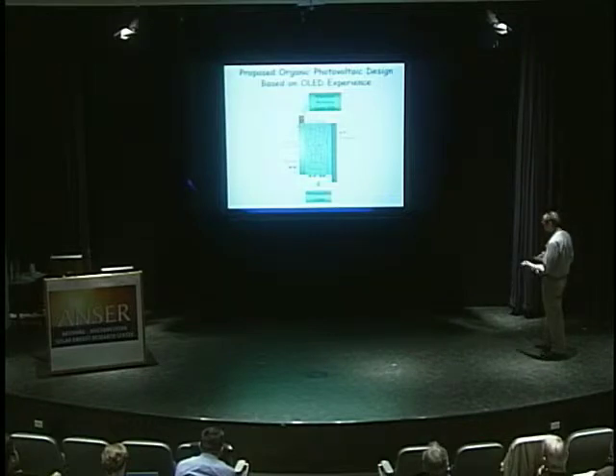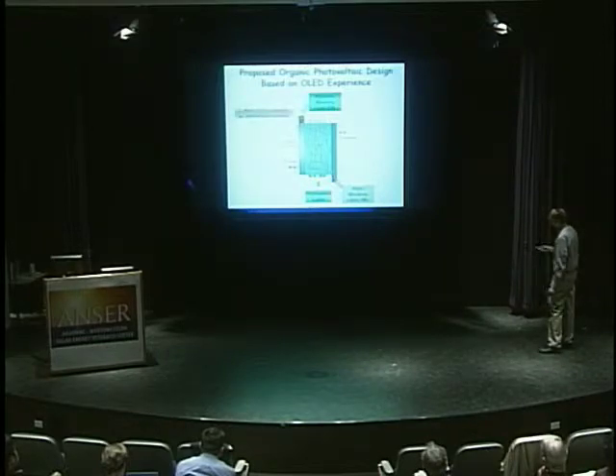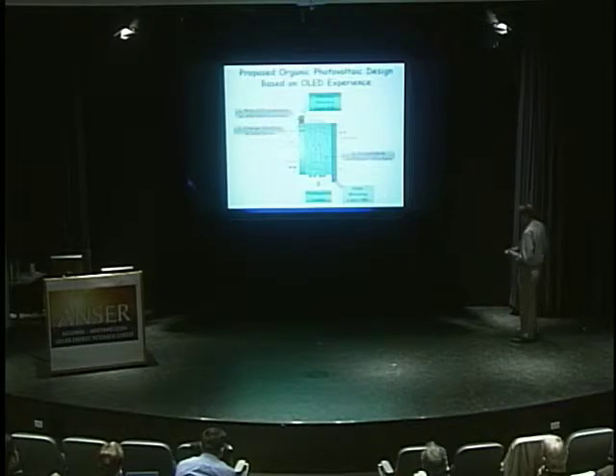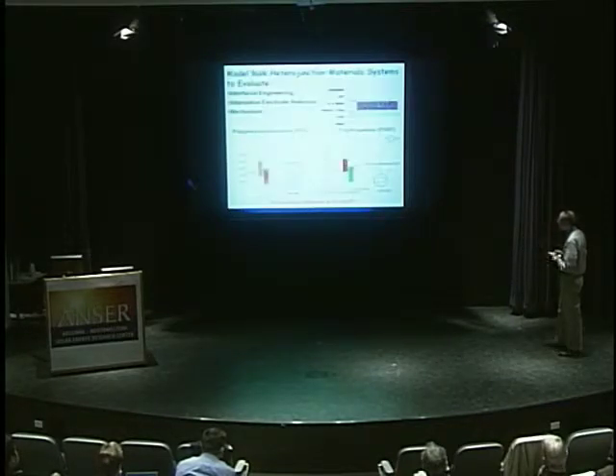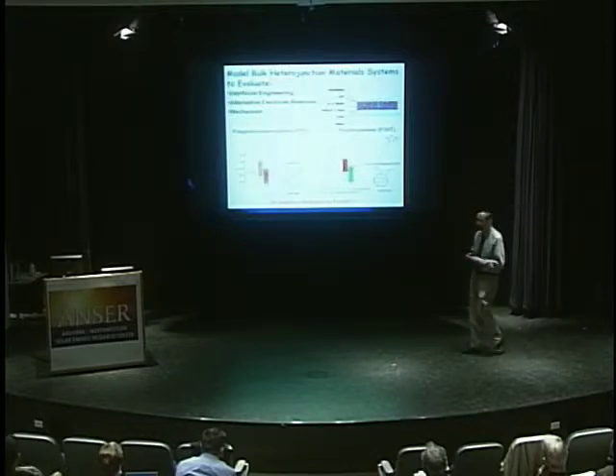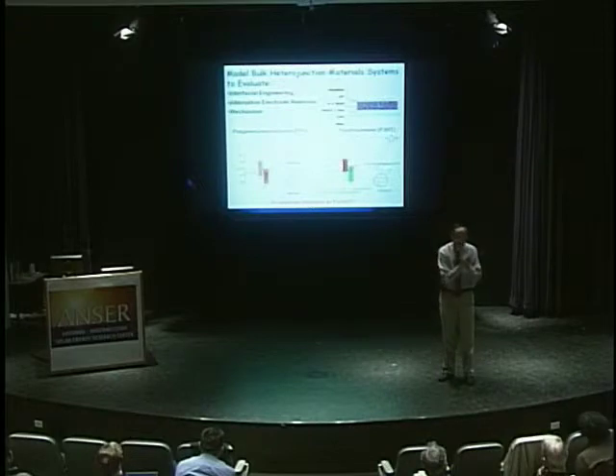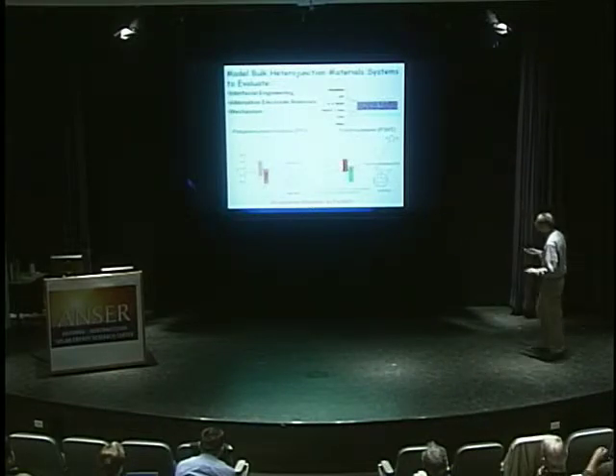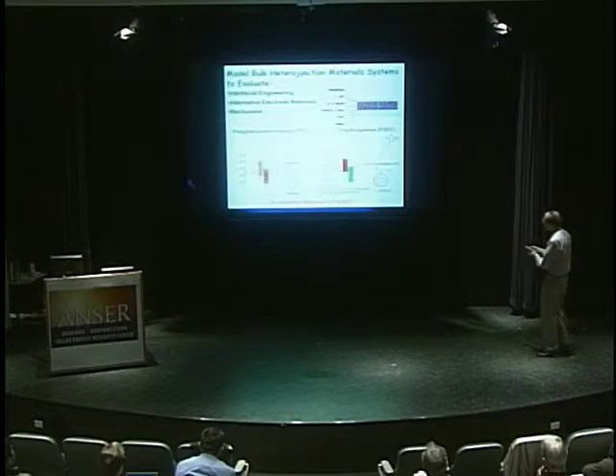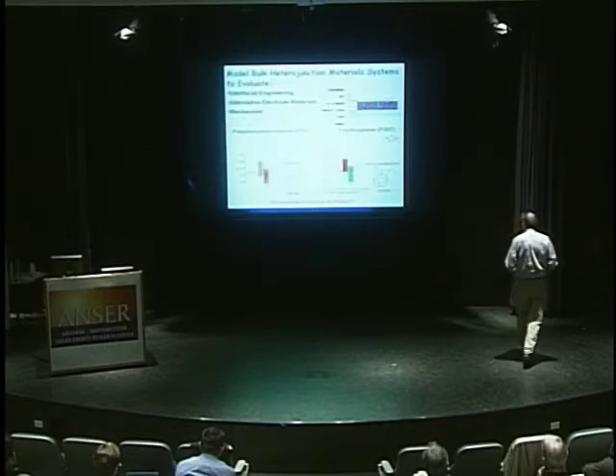Likewise, the photoactive layer, obviously we're going to need that. You can imagine by the same kinds of approaches putting in a hole blocking layer. New TCO materials as alternative anodes. I'll get into that. As I said, indium's in short supply. Charge blocking at the interfaces. And ultimately, we want a cross-linked multi-layer structure here. Now, I'll tell you more about that at the end, and interfacial stabilizers. So our first set of experiments, the game plan was to use known bulk heterojunction materials. We're going to use two that René told us about already, the polyphenylene-vinylene system and the polythiophene system. And we're going to keep those constant and turn on other aspects of other parameters that we want to introduce.